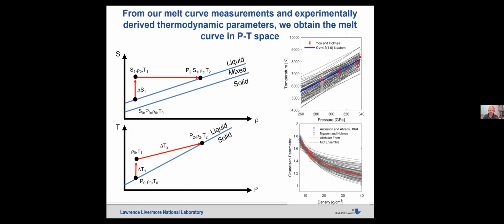So actually, from the pressure entropy plane, you can follow a two-step thermodynamic integration if you have some sort of second derivatives. And so what I'll walk you through is that in the entropy plane, so this is now entropy as a function of density, but you can think of this as pressure too, you can take your reference point on the liquidus, which will be the pressure at complete melting, and say the temperature. And you follow a two-step thermodynamic path.